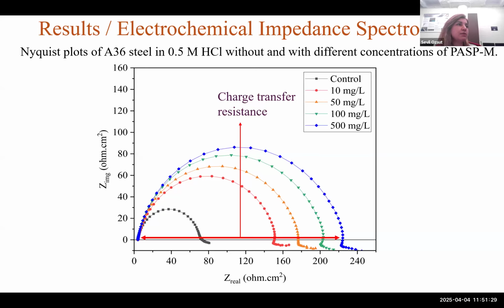The black one is for the control, with no inhibitor. We have a very small diameter, so it shows a lower charge transfer resistance. But when we look at the highest concentration of this inhibitor, we get a higher diameter, which shows more resistance to that charge transfer.